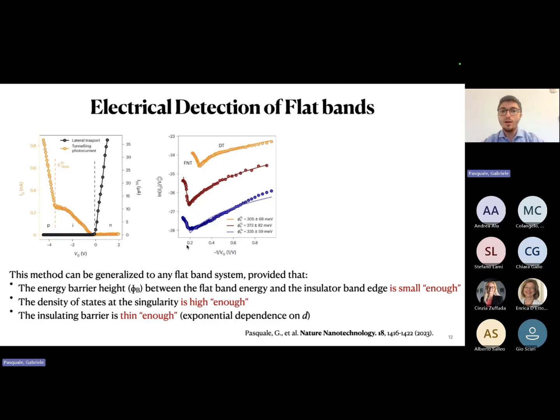We have defined a whole set of rules, guidelines, to generalize this effect to potentially any flat band system. But what I want you to focus on is the fact that the reason this method works so well is because it entails three different exponentials in the formulas. The current that you measure is exponentially dependent on the density of states through the effective mass, on the energy barrier of the dielectric, and on the thickness of the dielectric. So you can play with three different degrees of freedom to enhance the signal, which will be proportional to the density of states, which is naturally something you want when you want to study flat band systems.